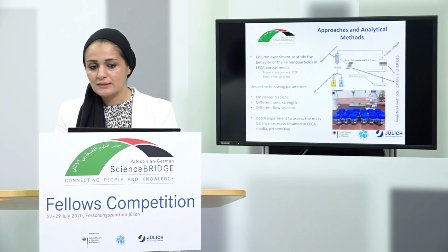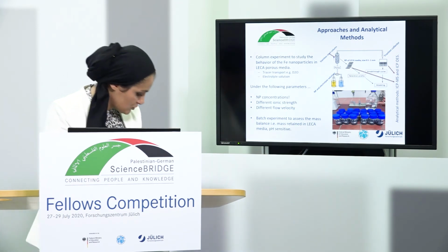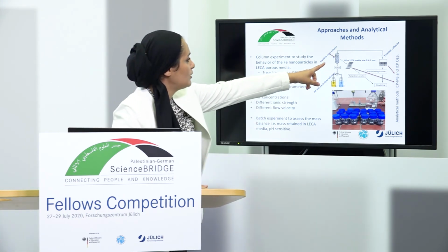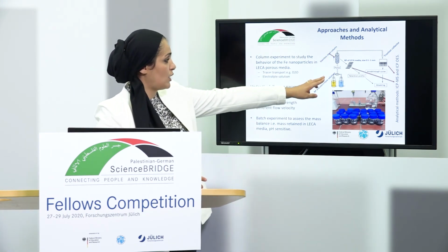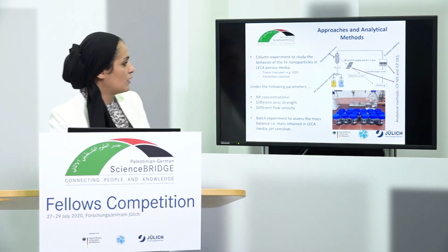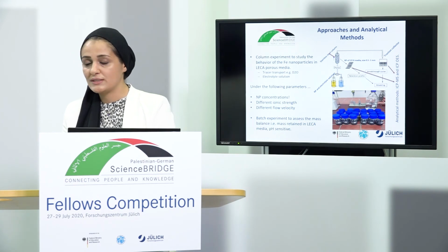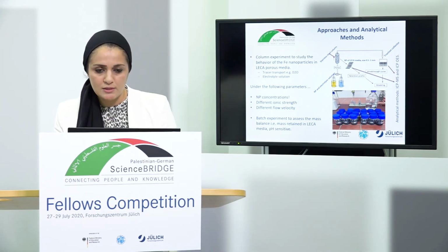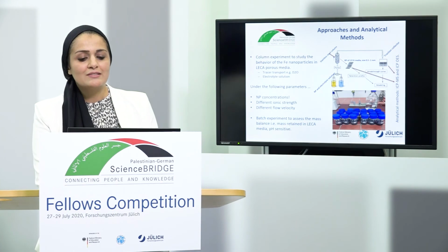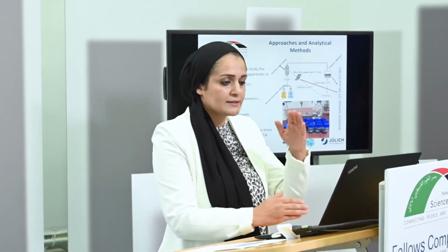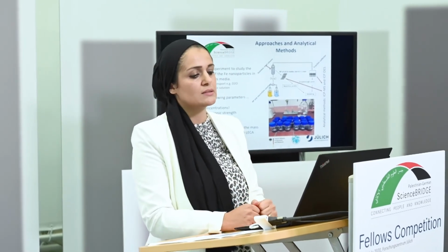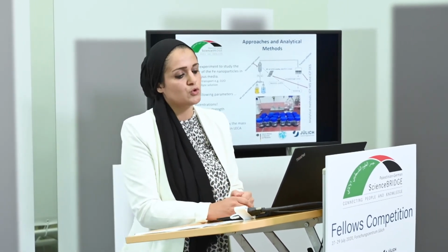The column is connected to a pump and injected with iron nanoparticles. After we collect the solution, we test it via ICP-MS or ICP-OES, and we see how many nanoparticles are retained in the LECA and how many are ejected in the solution.